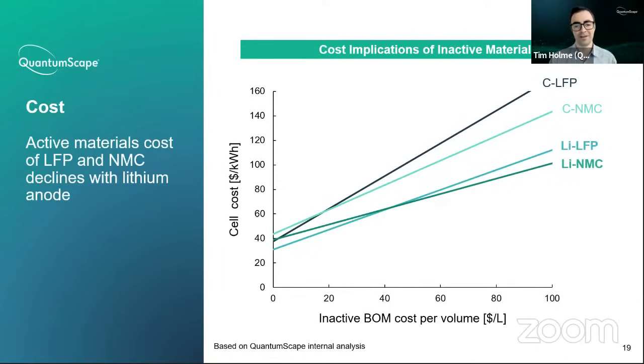But over time, one of the other trends that has been changing is supply chains are ramping up. Manufacturing innovations are coming online that are reducing the cost of these inactive components. If the cost of the inactive components becomes low enough, there's a crossover between these two lines, and the LFP cell would become the lower cost per kilowatt hour cell all in. And so that's another one of these trends that I think people are anticipating, is writing these cost curves down towards the left. So this crossover point also occurs if you have a lithium metal anode. If inactive component cost is high with a lithium metal anode and NMC cathode, the NMC is the cheaper cell. But as the inactive costs come down, there is also a crossover point where the LFP cell becomes cheaper on a dollars per kilowatt hour basis.